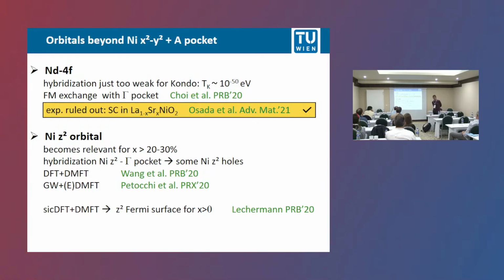And there are indeed two schools of thinking for the z squared orbital. One is here, the groups of Haule and Philipp Werner, where you have in particular this gamma pocket relevant for the z squared orbital. I told you that the gamma pocket is a neodymium or lanthanum derived orbital, but it has a strong hybridization with a nickel z squared. And because of that, you have something like 15 or 20% holes in your original nickel z squared orbital. This gamma pocket is not strongly correlated, and as I've shown you before, our point of view is that this physics, where you can maybe then have this 15-20% doped z squared orbital and its spin coupled to the x squared minus y squared orbital, we think that can be relevant physics for lowly doped neodymium nickelate, but since this gamma pocket is so different among different compounds and doping, we don't think it's the relevant point for superconductivity.